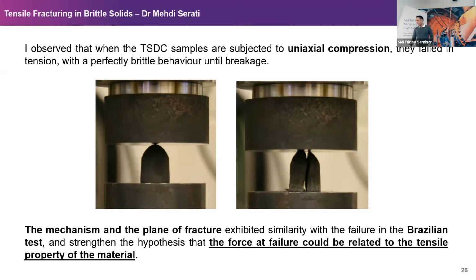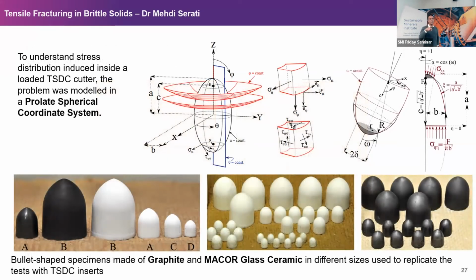So the question is, if you have the geometry and the load at failure, can you calculate the tensile stress induced inside your sample responsible for the tensile fracture? I could not find anything in the literature for that type of loading condition and sample profile that could give us an equation for the induced tensile stress. So what we did was replicate the test with different types of material, ceramic and very brittle graphite, at different sizes, and I had to introduce the boundary condition in a prolate spheroidal coordinate system.